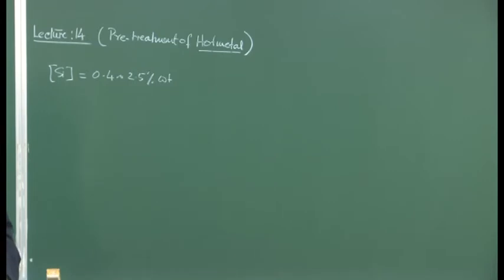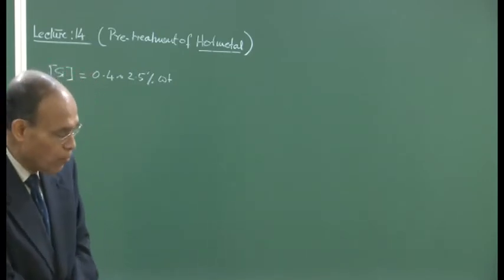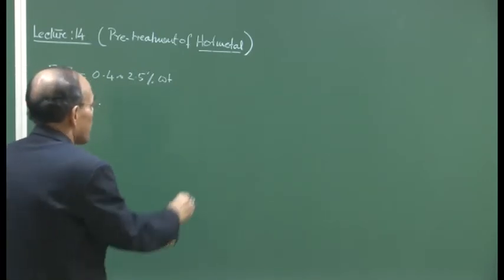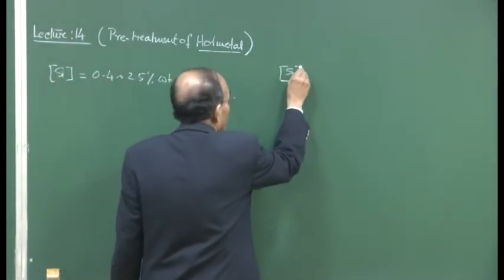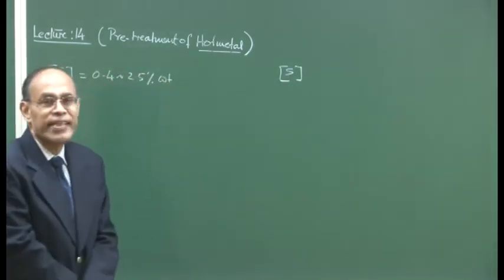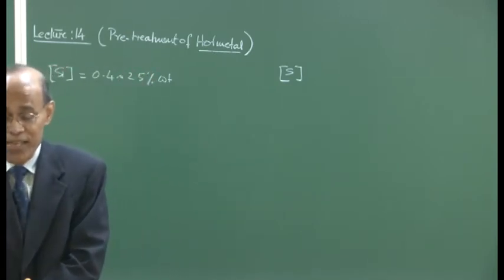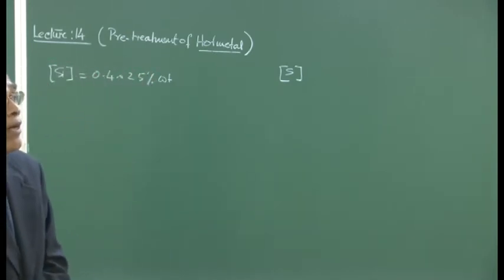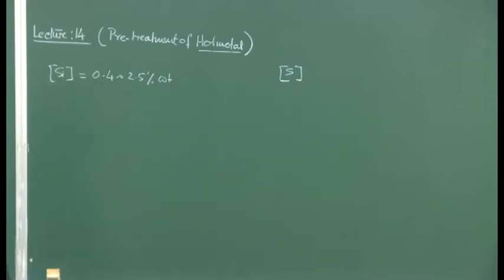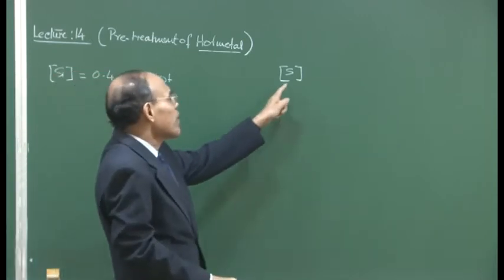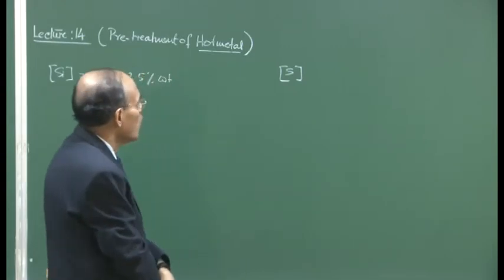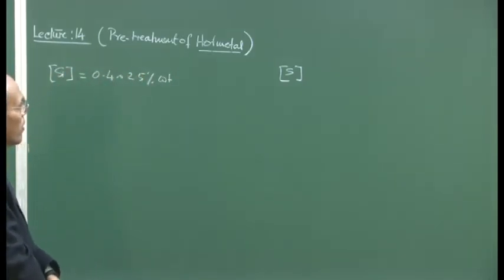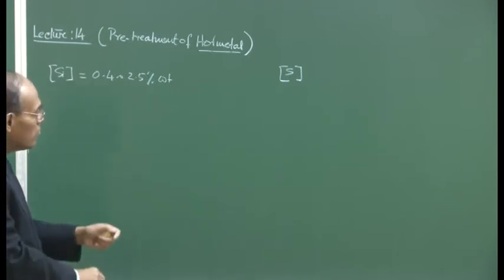Similarly, we have also seen, and we are going to discuss today much more lucidly, that sulfur removal can take place only under a reducing atmosphere. I have said in the class that we require a basic slag and we require a reducing environment, and the blast furnace is perhaps the most suitable place for removal of sulfur. But unfortunately, in the blast furnace we are not able to eliminate sulfur to a desired optimum level because of certain operating reasons.